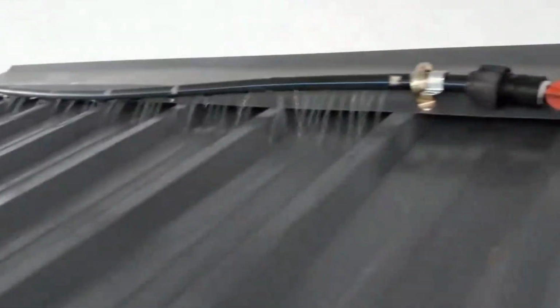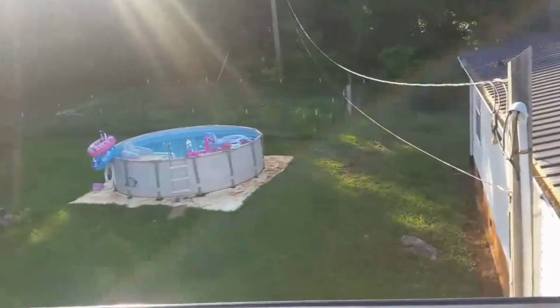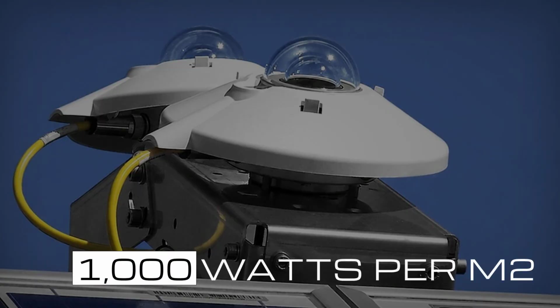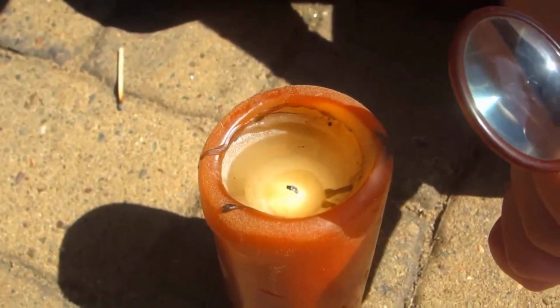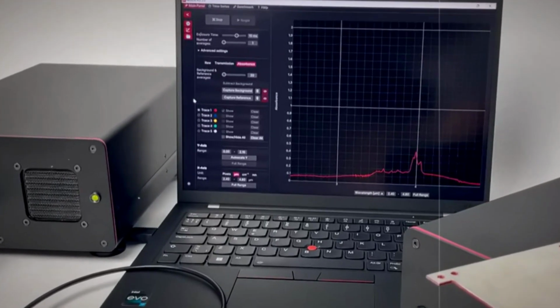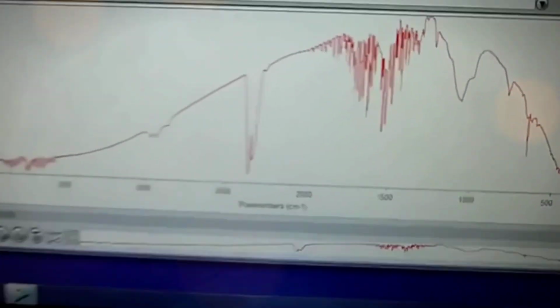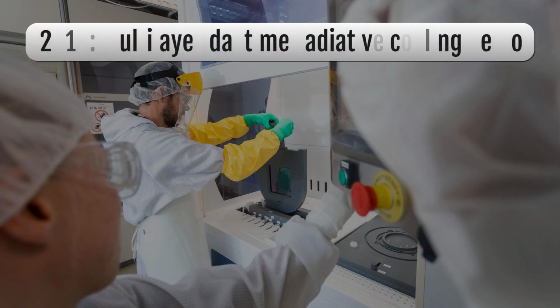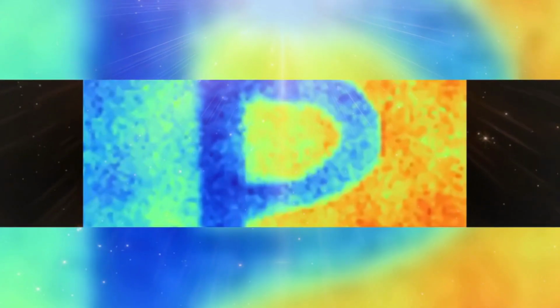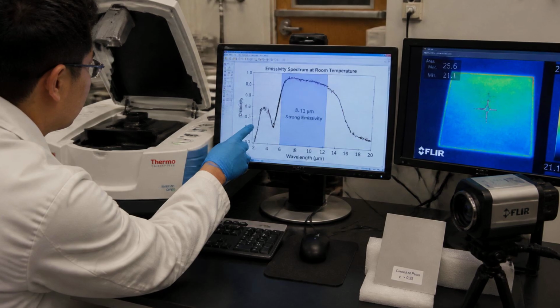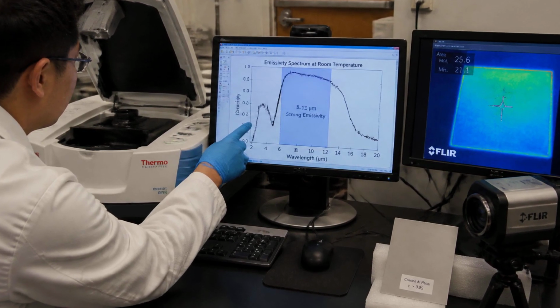Nighttime cooling is comparatively straightforward because there is no direct sunlight heating the panel. Daytime cooling is much harder. At midday, sunlight can deliver close to 1,000 watts of energy to every square meter of exposed surface. Because the radiative cooling effect may only remove a few dozen watts per square meter, even a small amount of absorbed sunlight can overwhelm it. Researchers therefore develop surfaces that reflect nearly all incoming sunlight while still releasing infrared energy through the atmospheric window. In 2014, researchers demonstrated a specially engineered multi-layer material capable of remaining below the surrounding air temperature in direct sunlight. The structure reflected approximately 97% of incoming solar energy while emitting strongly in the desired infrared range.